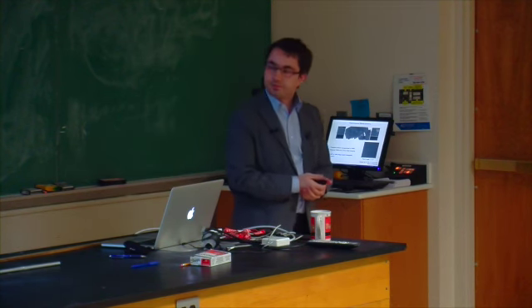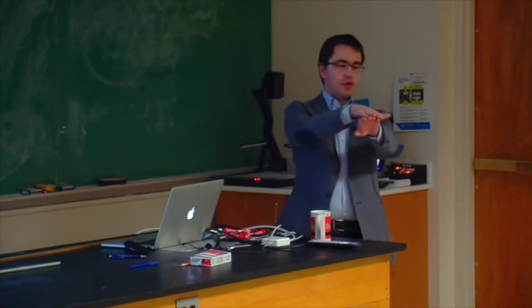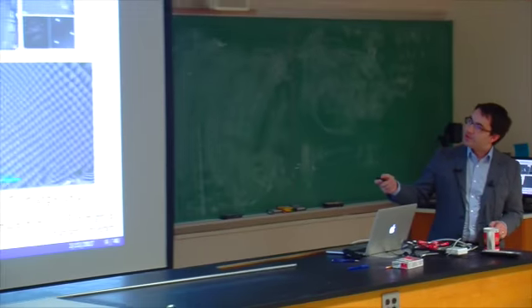This is an experiment from the group of Philip Kim, where Hyobin Yu looks at what happens if you have two layers with a very close twist angle between them. So I have two layers of graphene on top of each other with an extremely small angle between the two. Here it's 0.8 to 0.2 degree. Here it's not quite as uniform.